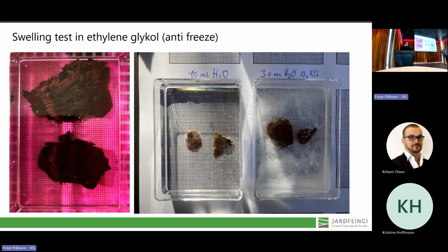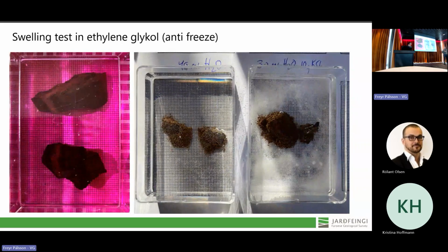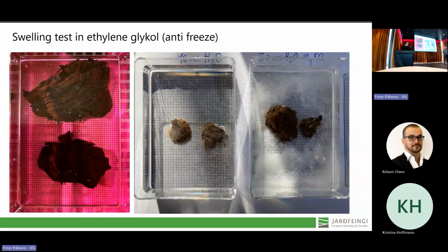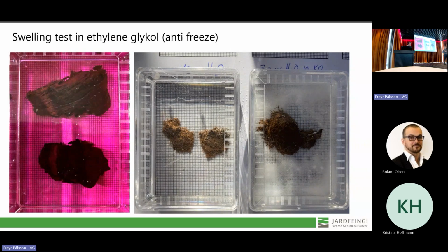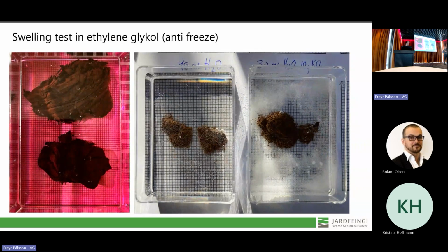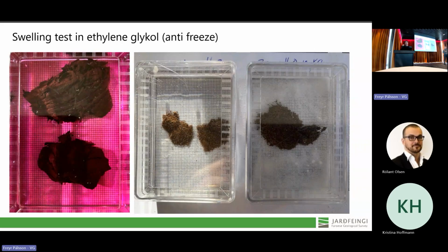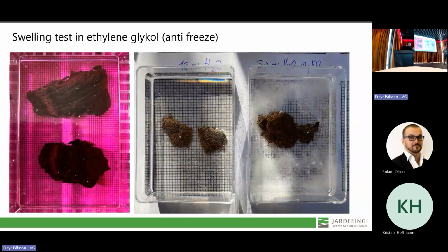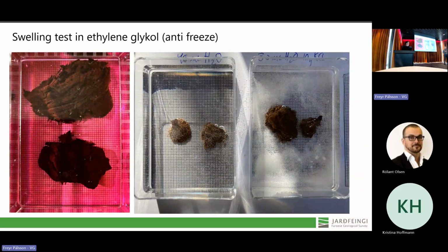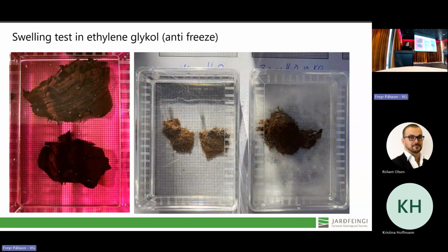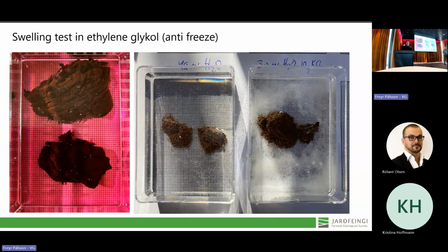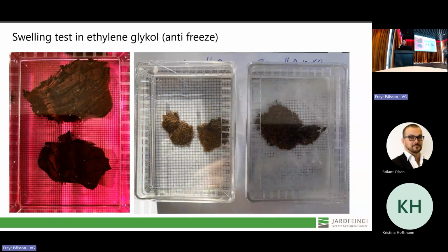For testing aggregates, maybe Iceland is doing it differently, like the UK, where they at least introduce some kind of water absorption test, because it's not only swelling clays that are an issue, it might also be the freeze-thaw process. So you leave aggregates out in the cold, and those that are porous or microfractured will disintegrate. And salt can also be a problem, but maybe less so.